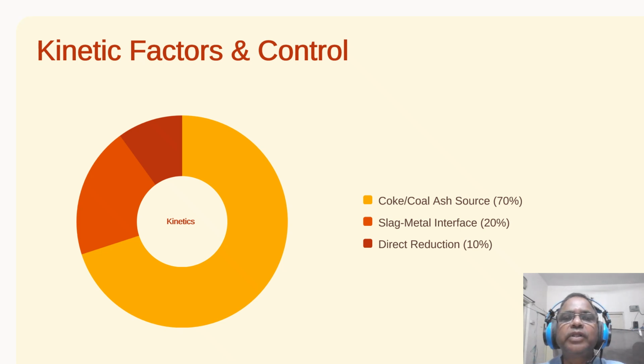So, where is the silicon actually coming from? Check out this pie chart. That massive 70% orange slice. That's the coke and the coal ash. Most people think the slag is the main culprit, but it's actually the fuel itself. Only 20% comes from the slag metal interface. So, what is the result? This means if you have dirty coke with high ash, you are fighting an uphill battle from the start. You cannot just fix it with slag chemistry. You have to look at your raw material quality first.